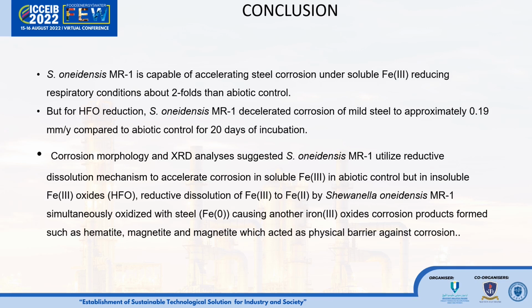Corrosion morphology and XRD analysis suggested that Shewanella utilized a reductive dissolution mechanism to accelerate corrosion in soluble iron 3 compared to the abiotic control, but in insoluble iron 3 oxides, in brackets HFO, reductive dissolution of ferric iron to ferrous iron by Shewanella oneidensis MR-1 was simultaneously oxidized with steel, causing other iron 3 oxide corrosion products to form such as hematite, magnetite, and vivianite, which can act as a physical barrier against corrosion.